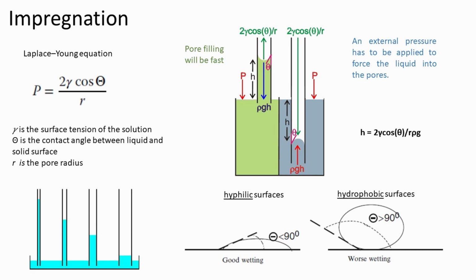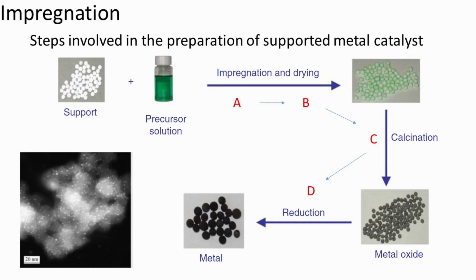Oxidic supports are usually hydrophilic, but this depends on the concentration of hydroxyl groups on the surface of the oxide nanoparticles. In case of hydrophobicity, it is advised to use a less polar solvent such as ethanol or isopropanol. The disadvantage is that the maximum concentration of the metal precursor is usually lower in these solvents. Impregnation is followed by drying.